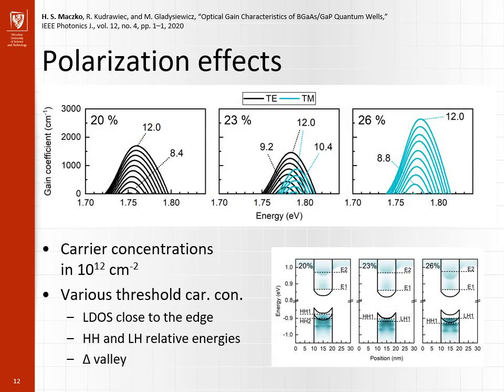Polarization of the spectra depends on the holes involved in the optical transition. Since the highest density of states close to the band edge occurred for the light holes in the tensely strained quantum well, the gain spectra for transverse magnetic polarization for the quantum well with 26% of boron arsenide have the highest values. Delta valleys seemingly have the most influence on the threshold carrier concentration at which the gain appears.